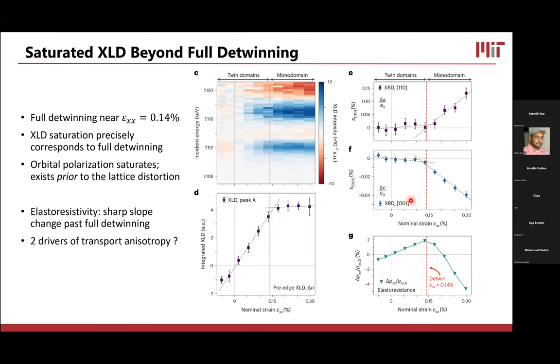Okay. So now to reveal the rest of the plot, this red line here corresponds to the point where the sample has become fully detwinned. At every strain value where we were taking XLD data, we were also taking X-ray diffraction data. So at these points, we're looking at the in-plane lattice constant aligned with the stress direction. And in this second panel, we're looking at the out-of-plane lattice constant. What you can see is that for a small compressive range up to a medium tension range, these lattice constants are essentially flat. That corresponds to the strain range where the sample is being detwinned.